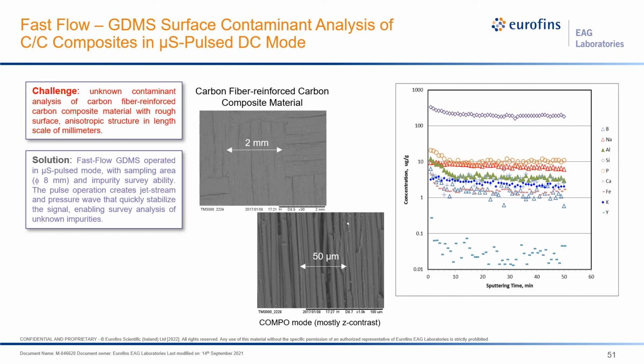The solution is fast flow GDMS operating in microsecond pulse mode. Of course, it has a sampling area of 8 millimeters, which can cover not just one, but much larger features. And because GDMS has a impurity survey ability, it makes it perfect for detecting unknowns. The pulse operation can create a jet stream and pressure waves that can quickly stabilize the signal, enabling survey analysis of unknown impurities. Here is the data we collected from one of the commercial CMC samples.